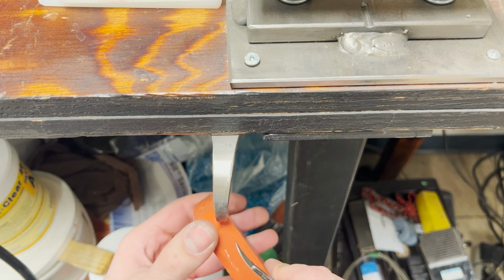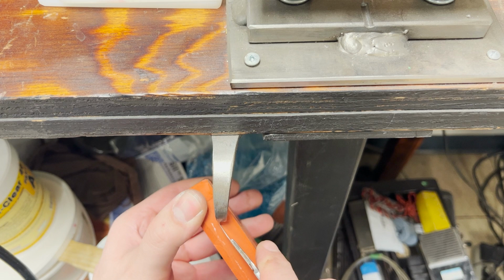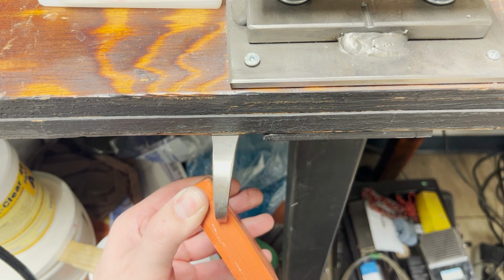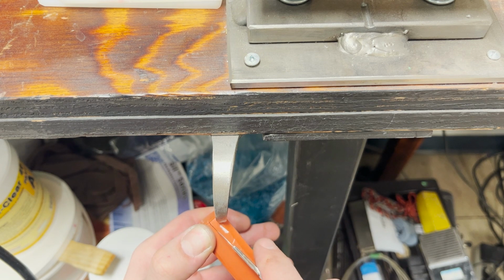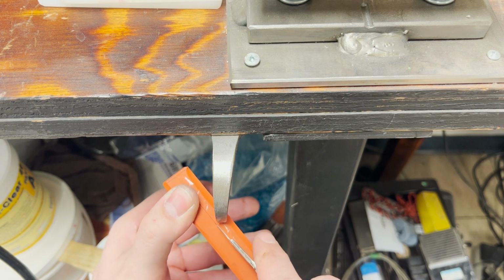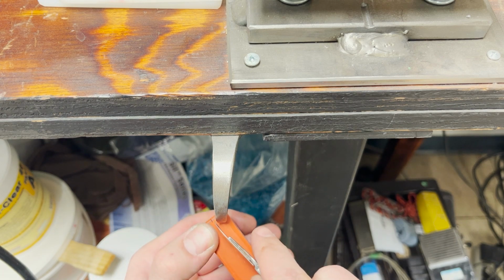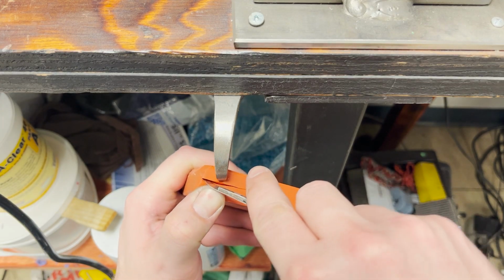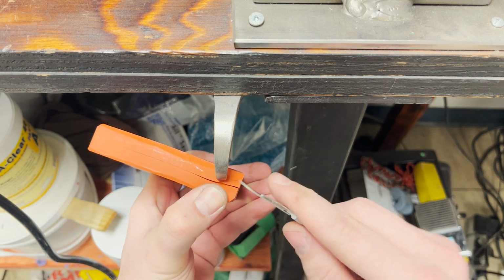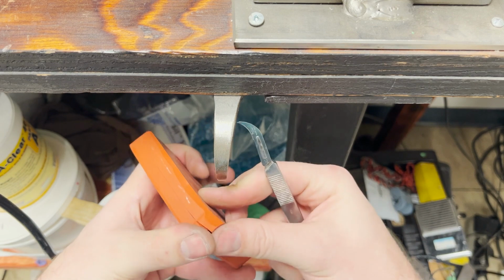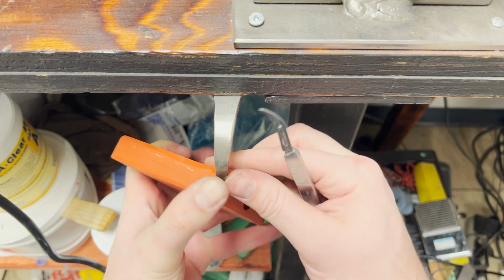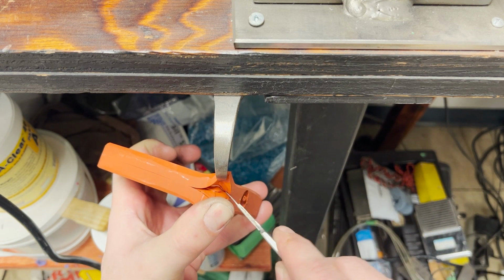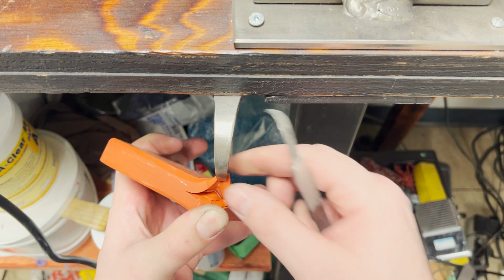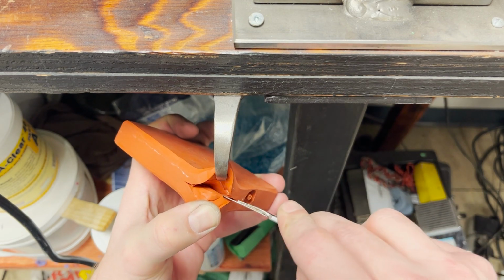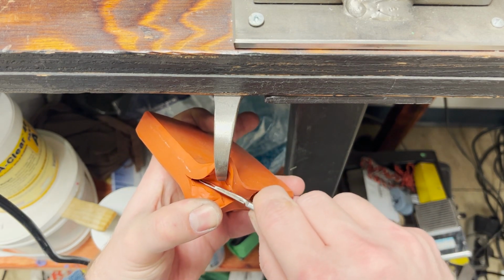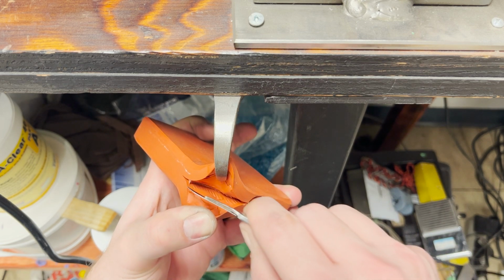So cutting this material is pretty standard. I would say it's definitely on the firm side. It's, I believe, on a Shore hardness scale between 65 and 80, which isn't too bad. I am typically using Shore hardness of 40 when it comes to my RTV rubbers, so comparatively this is about twice as hard. Now, I actually quite like that, especially for this particular mold, because it's so wide and flat. I'm going to need that rigidity to resist the clamping pressure that I'll need to hold it together properly when I inject the wax. And because it's so wide, I'm probably going to have that wax temp up a little bit higher than I'm comfortable with to make sure that it gets into all those details.